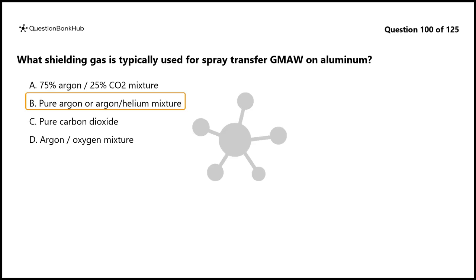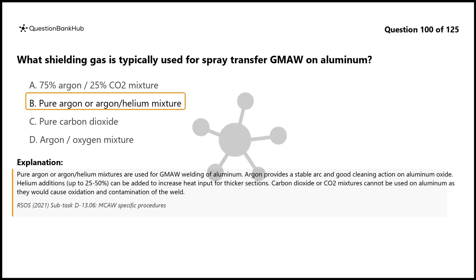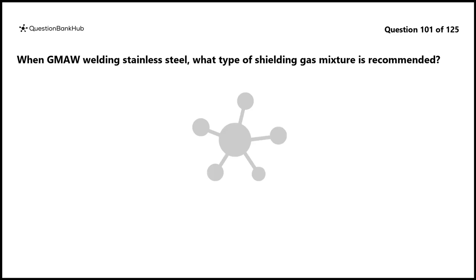Pure argon or argon/helium mixture. Pure argon or argon/helium mixtures are used for GMAW welding of aluminum. Argon provides a stable arc and good cleaning action on aluminum oxide. Helium additions, up to 25 to 50%, can be added to increase heat input for thicker sections. Carbon dioxide or carbon dioxide mixtures cannot be used on aluminum as they would cause oxidation and contamination of the weld. Question 101. When GMAW welding stainless steel, what type of shielding gas mixture is recommended?